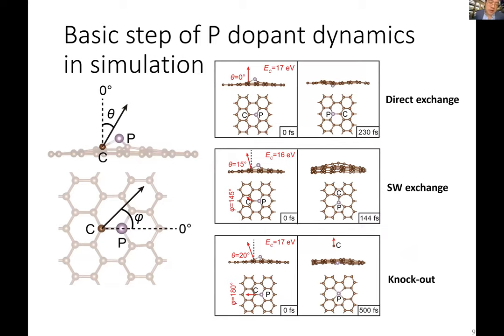So we start to do some models of this process. Even at 60 keV, the electron is still moving at about 45% of the speed of light. So we have to use relativistic kinematics to solve for the collision between the electron and the carbon atom. And that can only happen when the electron is within 10 femtometer, or 10 to the minus 14 meter, away from the nucleus of the carbon. But when you get that close, it can actually give quite a big kinetic energy to the carbon atom. So 16 electron volt or 17 electron volt.